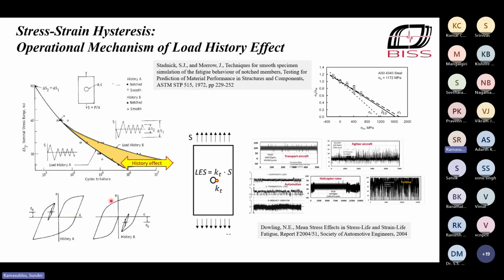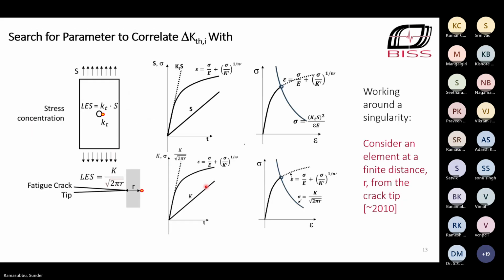So it turns out hysteresis is the culprit. It's hysteresis on the stress strain response, which is responsible for both the mean stress effect as well as the load history effect. Now, you can look at a notch root, but you can also look at the crack tip. So here's the notch root. The local stress is given by stress into stress concentration factor. That's a local elastic stress. But I can also look at the crack tip at some distance from the crack tip, and I'll get the elastic stress at that point through this equation.